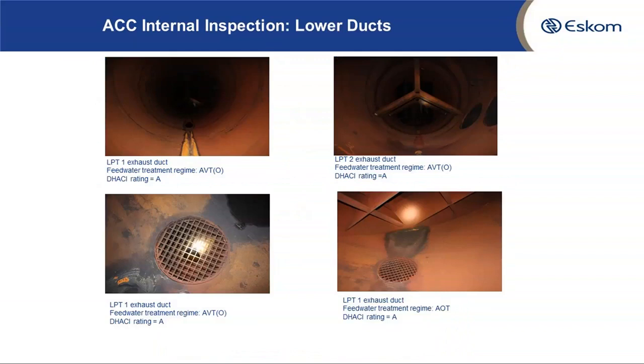In terms of the findings from the inspections, the two lower ducts, the exhausting ducts, this is good appearance. We can see there is hematite formation, even though the unit at the time was on AVTO, but one can tell that the hematite formation was not so uniform, though there are no obvious areas of severe corrosion when you're looking at the first top images. Very good protection, though hematite could also be improved.